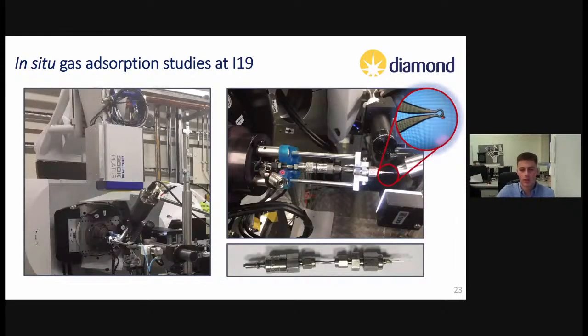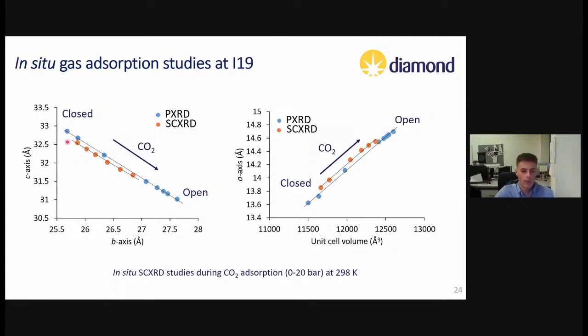And we've also looked at this using single crystal X-ray diffraction. Again, we put our sample on a mylar tip. So we start with the crystal glued to the mylar tip, packed inside one of these quartz capillaries, and that fits inside one of these gas cells, which again we can sit onto our diffractometer and collect diffraction data under a positive pressure of gas. We did the same thing again, CO2 at 298 Kelvin, and what we see is the framework is able to reopen as we gradually increase that CO2 pressure.